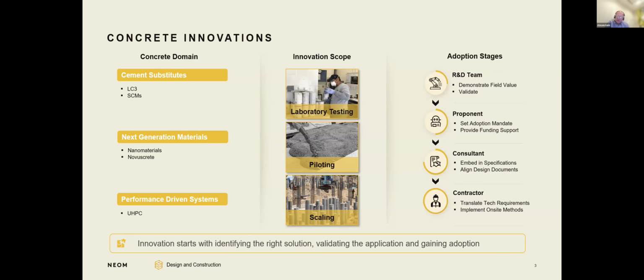We've done quite a bit of work on clays, LC3, and we have used and calcinated quite large volumes of clays. What we noticed with the clays was that we had quite a lot of variability across the quarry and low kaolinite content. So we were only able to achieve low strength grades with the material that we had access to. So I'm quite pleased to see that one of the first initiatives that you have is to map out the deposits within the kingdom so that we can understand where the good quality clays are